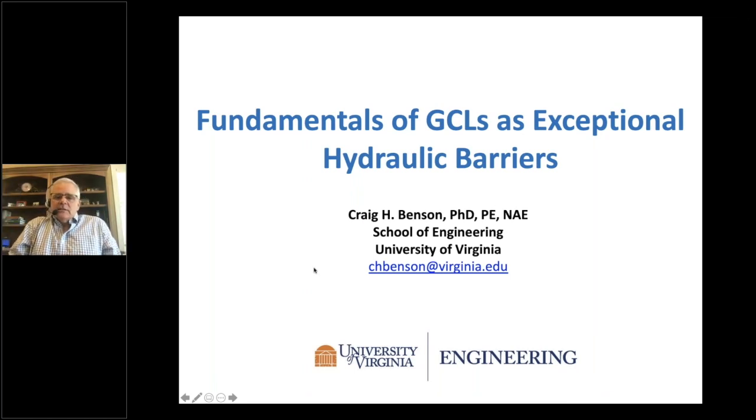The bentonite is gritty, granular stuff when it's dry, but as soon as it gets wet and begins to hydrate, it's soft, mushy stuff. Any stress concentrations on the surface will tend to cause displacement of the bentonite in the GCL, causing thin spots in the GCL. That's just something we don't want to do. We want to get the GCL down, get a geomembrane on top if it's not a laminated product, and then get it covered as soon as practical.